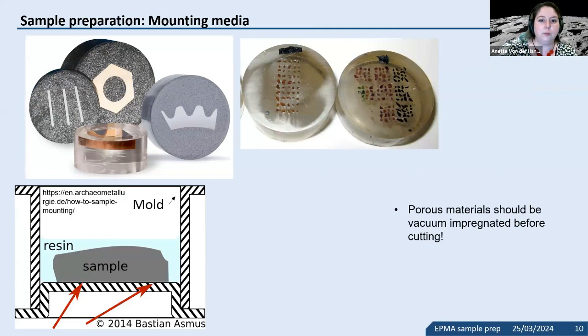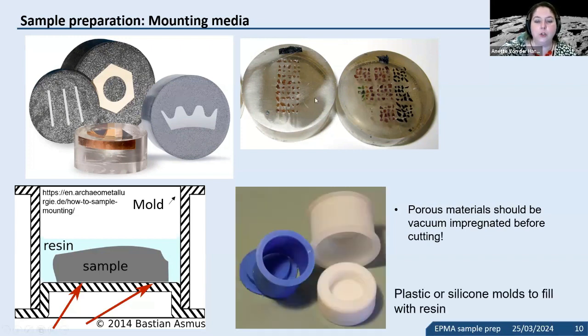But if you do it yourself, mounting media are very commonly done in-house. There are different types where you just embed your sample in a mold with some resin, have it cure, and then you polish the entire thing. There are different types of molds, silicone molds and plastic molds, available for that. You can make grain mounts on an adhesive surface and then fill it, or you have larger samples. Important is that if you have a porous material, it should usually be vacuum impregnated before cutting and before embedding.